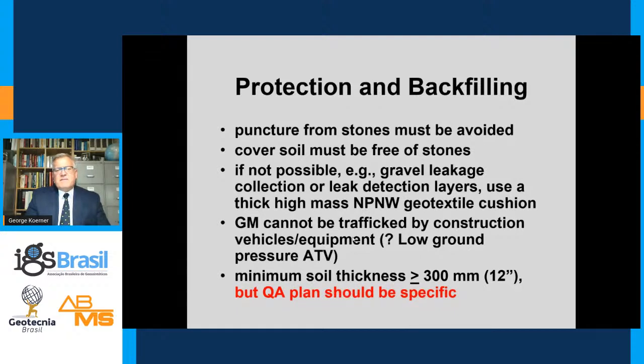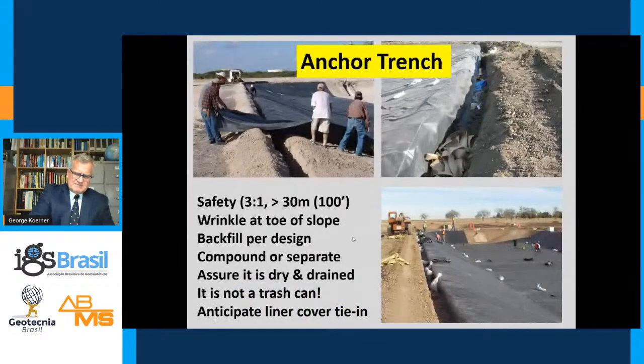The ATV typically has special precautions, like entering the geosynthetic at a 90-degree angle, no fast starts, no on-off the geosynthetic. It has to remain on there. In addition to that, if the material is to be trafficked, it should have a minimum thickness of cover soil over top of it. That's typically greater than 300 millimeters or 12 inches. Some regulatory agencies, like the Corps of Engineers, want 450 millimeters or 18 inches. But all of this is specified in the QA documents, the QA plans.